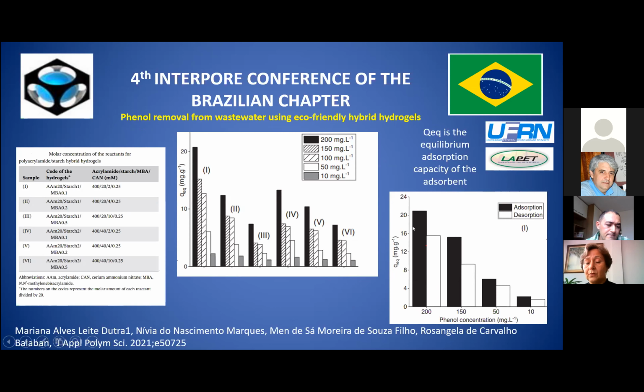So it was possible to observe a high capacity of adsorbed phenol inside the hydrogels, and it was possible to deliver the phenol from the same hydrogels. It is very interesting because you can reuse the hydrogel and the phenol delivered in the aqueous medium.